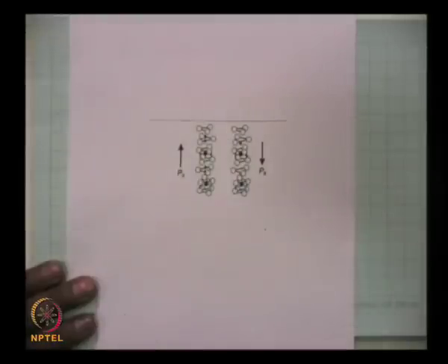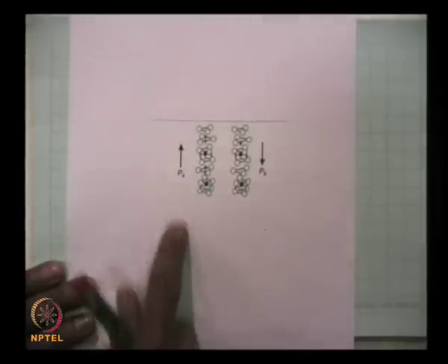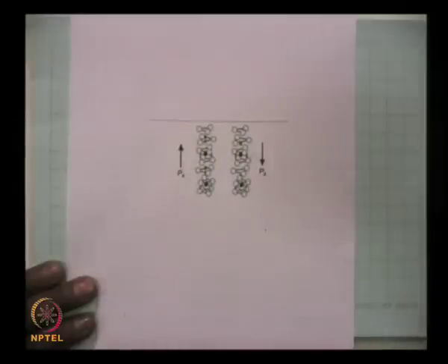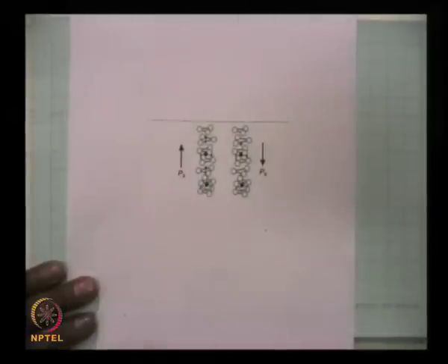The lithium atoms can be above the oxygen plane or below the oxygen plane, both are stable situations. Because of this asymmetry, if the lithium atom is sitting in this position, the spontaneous polarization is pointing up. If you displace the lithium into the lower surface below the oxygen plane, the spontaneous polarization reverses itself. Actually, this is just this one rotated by 180 degrees, it is the same.